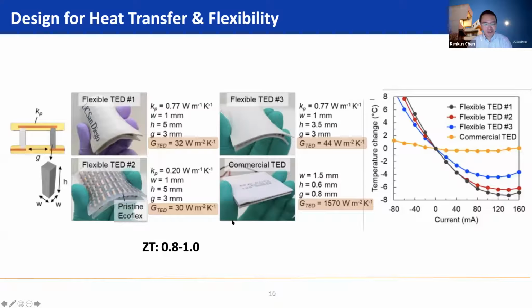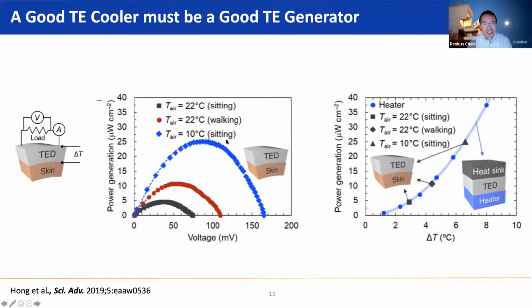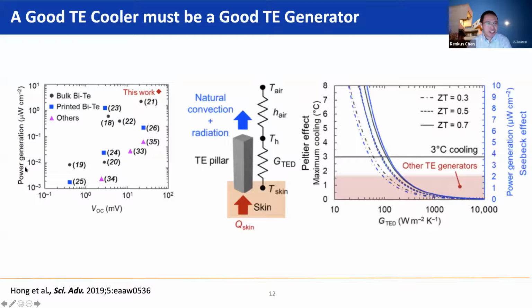These are all based on simulation, and the materials that we use are just commercially available thermoelectric materials with ZT around 0.8 to 1. And we can also see this exactly same device is also very good as an energy harvester for power generation from the skin temperature. I will not go into detail, but basically you can see in terms of the energy that you can harvest in terms of power density, this is much larger than what has been shown before. And the reason is exactly the same as I mentioned before. You need to have a good thermal design to dissipate the heat from the skin to the environment, even for power generation. And so as you can see here, that's because the Peltier cooling effect and the Seebeck power generation effect obviously are correlated.